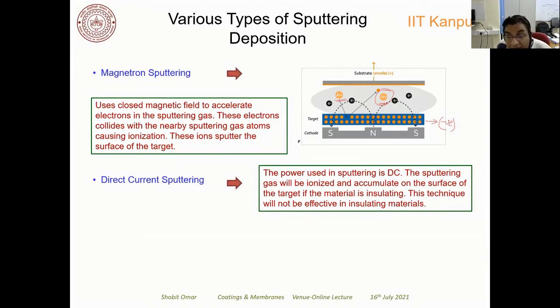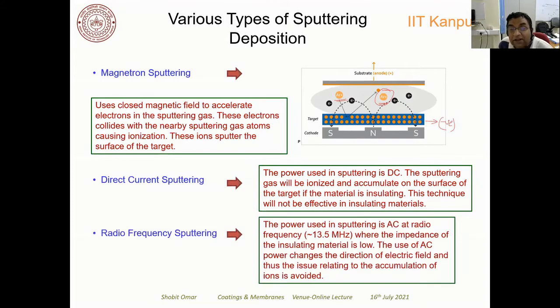So what is the solution for that? The solution is to use a radio frequency sputtering technique, which basically changes the electric field at a frequency of 13.5 megahertz. Now, why do we use this frequency? Because at this frequency, the impedance of most materials becomes very low, right? So we basically make the material conducting at this frequency.